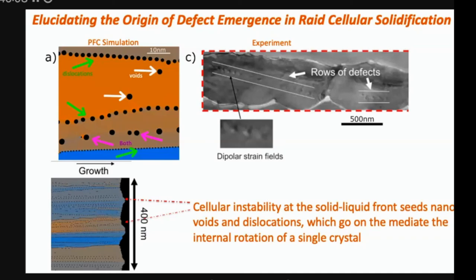These cellular structures merge into more or less one gradually undulating interface. But there are small scale hiccups to it. These hiccups kind of bounce around as the interface is moving. Think of them like turbulence. And they spawn off these voids that then move their way through the solid. And these lines of voids either can stay as voids or themselves, because of the scale involved, they're nanoscopic, transform into lines of dislocations as shown here.